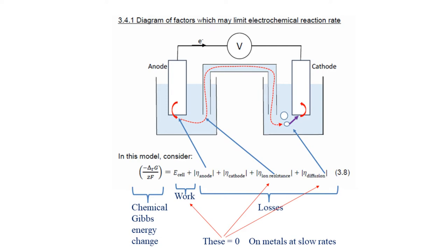So in this equation 3.8, I'm assuming this E cell is zero, I'm not drawing any useful power, and two of the obvious losses, the ion resistance terms, also any possible electronic resistance terms and a possible diffusion layer resistance terms, all of those have zero loss. And if all of those have zero loss, then I have only essentially one thing to consider per electrode to work out how fast this reaction happens.